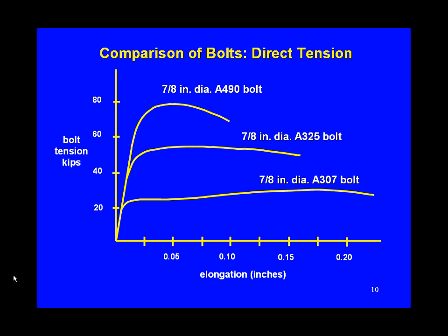It's better to look at things graphically. We have bolt tension obtained from a tension test. For a 7/8-inch diameter A307 bolt, the curve looks like mild steel — there's a rounded knee region and steel at these levels doesn't have a well-defined stress-strain curve. Moving up to the A325 bolt, strength increases but ductility has gone down a little bit. The A490 bolt is higher again in strength and again has slightly reduced ductility, emphasizing that steel is inherently ductile but if you keep pushing it, it gives up on ductility.